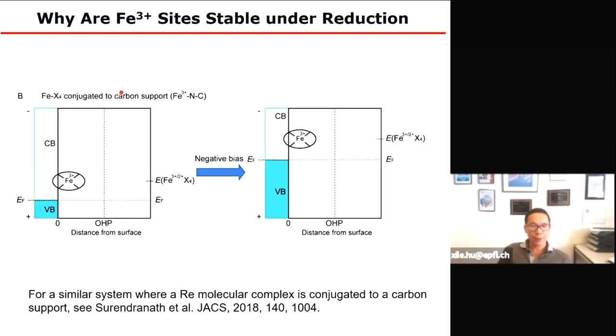However, now we think we have a really particular system of cooperative catalysis, where the iron sites are electronically conjugated to the nitrogen doped carbon. In this case, this is the Fermi energy of the metallic structure. The iron 3 site is here. They are coupled. Now, if you move this energy level up, this one also will move up because they are electronically coupled, so that you never have a situation where this will be more negative and you do electron transfer.